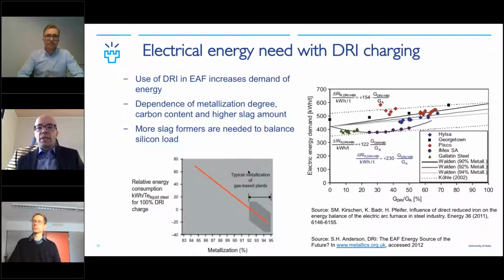If we continue with the DRI, we see that the use of DRI will increase the demand of energy, and it depends on the metallization degree and carbon content of DRI, and there will be also higher slag amount because metallization is not 100% in DRI. And we have to use more slag formers to balance silicon load in electric arc furnace.